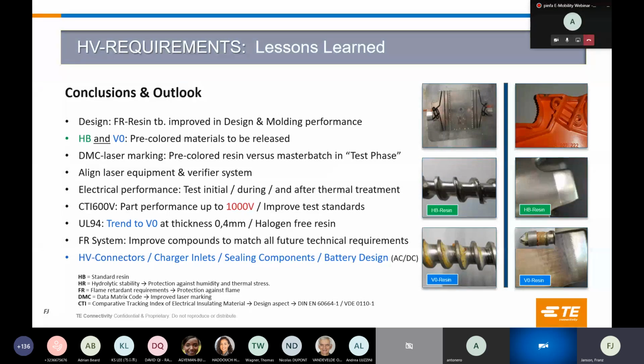Yeah, as I already mentioned, we still have the focus to design parts in HB and V0 materials. We need to improve the laser marking performance on the parts. Therefore, we analyzed today the solution by adding some master batches for the laser marking of the additive package in the materials during the molding side. We go also in the test phase for pre-colored materials for laser marking. Therefore, we need to align the standards in the laser equipment and also in the verifier system.